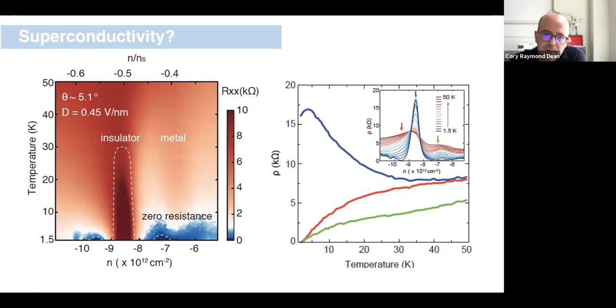Okay, so the final initial finding that we had was the question of whether there's superconductivity in the system. So this remains for us kind of an open question. Initially, at least on one of the devices that we measured, we were able to observe some pockets of response around the insulators. So we doped either positive or negatively relative to the insulator. There appears to be the onset of some low resistance or zero resistance state. I'm a little bit hesitant to definitively call this a superconductor for reasons that were alluded to a little bit earlier today. One is that a similar response was also measured in twisted bilayer graphene. Eventually, the conclusion was that that probably is not necessarily evidence of superconductivity, but may rather be evidence of some temperature-driven reconstruction of the Fermi surface, for example.